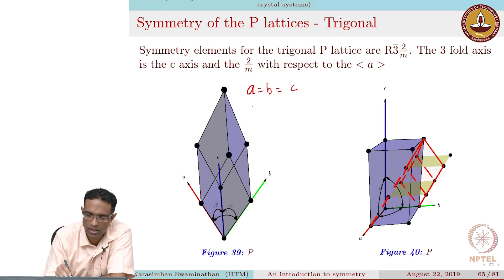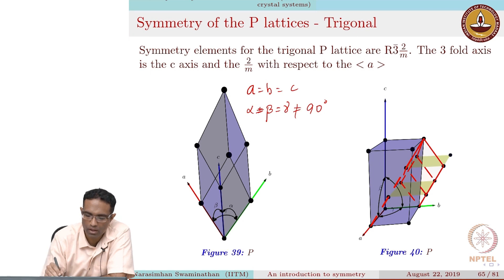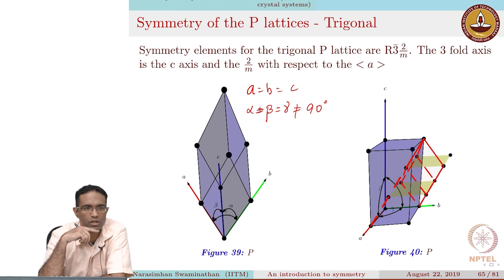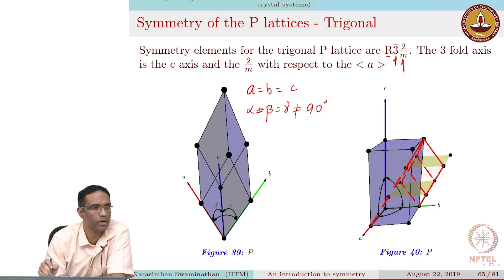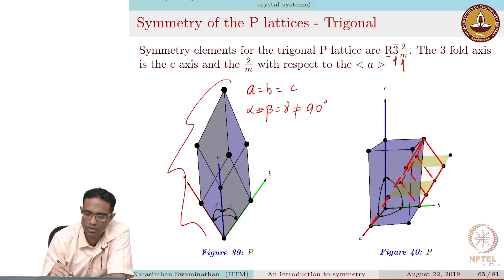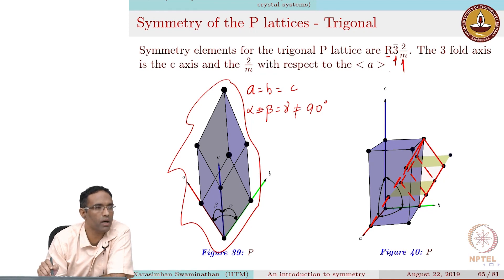We said that it was A equal to B equal to C, alpha equal to beta equal to gamma, but none of them are actually equal to 90 degrees — just alpha equal to beta equal to gamma is sufficient. The symmetry of this trigonal lattice is represented using R, 3-bar, and 2 over M. However, it is difficult to see with respect to this unit cell what the 3-bar and 2 over M actually represent.